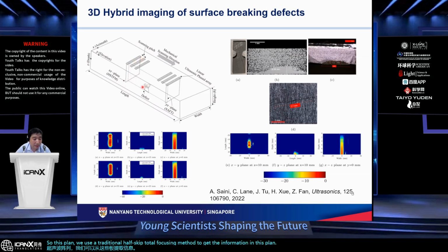And then because the defect is three-dimensional, we scan the transducer along the third dimension. Of course, we are not only stitching the images together, but we also apply a certain imaging algorithm, like in this case, the synthetic aperture focusing method, to do the third dimensional imaging. So this shows a few defects in simulation as well as in experiment. And we are also doing experiments with some complex shape defects. This is a real fatigue defect coming from thermal fatigue loading. With our imaging method, we are able to reconstruct these defects relatively accurately using the methodology we developed. Okay, so that's for the three-dimensional defect case.